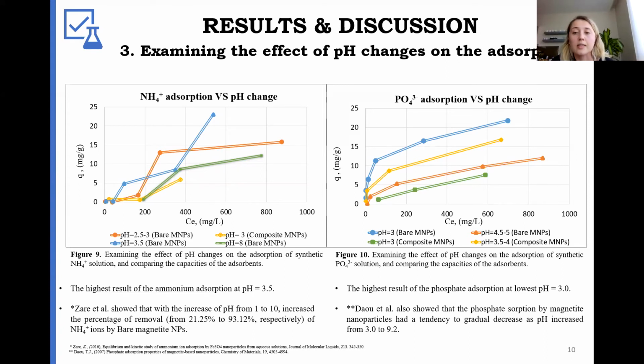On the other hand, the highest result of phosphate adsorption was obtained at the lowest pH, which was 3. With respect to this, Daou et al. showed that the phosphate adsorption by magnetite nanoparticles had a tendency to gradually decrease as pH increased from 3 to 9. Furthermore, the effect of composite form similarly resulted with the phosphate adsorption.